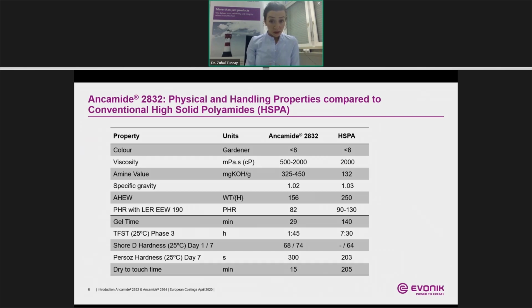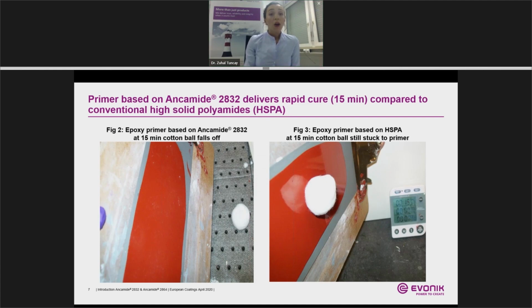Another significant difference to the competitive system is the dry to touch time, which is determined as 15 minutes for 2832 and 205 minutes for the competitive. One of the methods to determine the dry to touch time is the cotton ball test. Maybe some of you know that method already. In this simple method, used usually in refinish applications, as soon as the primer is sprayed to the surface, from the beginning on, every 2 minutes, the cotton ball is rubbed on the coating surface. If the cotton ball doesn't stick on the coating or doesn't leave any residue, at that point the primer is dry and can receive the top coat. And that was the case for 2832 after 15 minutes, and for the competitive system after 205 minutes.